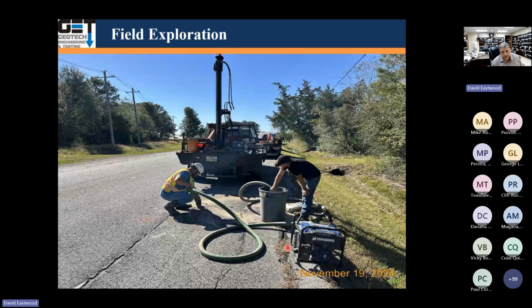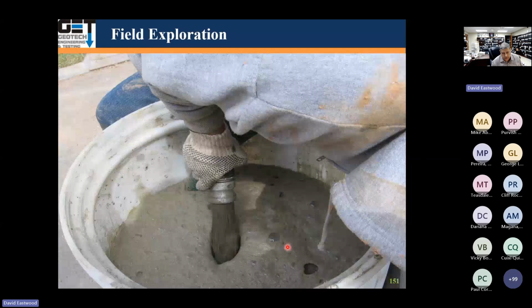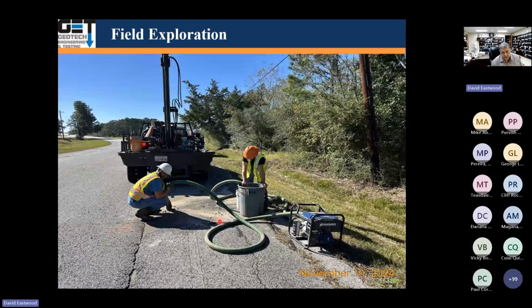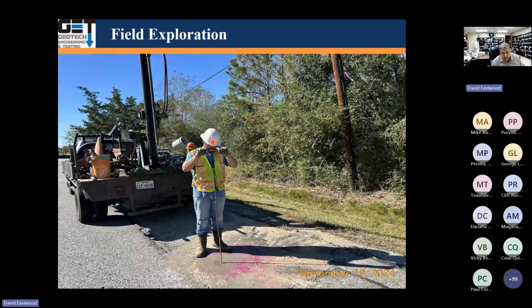When we finish the borings, we grout the holes. We fill them up with cement and grout, cement and bentonite to fill up the hole. Just mix the whole thing together in the bucket and push it under pressure from bottom up. Fill up the hole. We probed it, to make sure that the hole was grouted properly, so that there's not going to be a hole there, or somebody step in it.